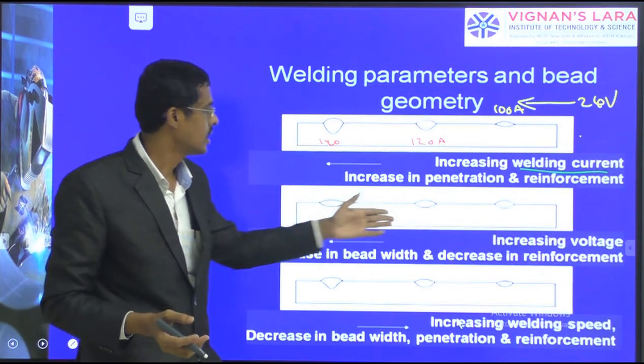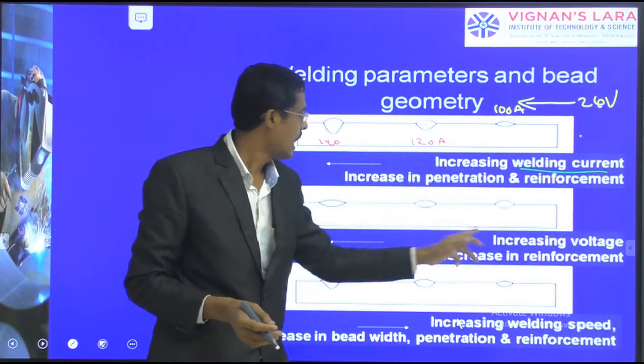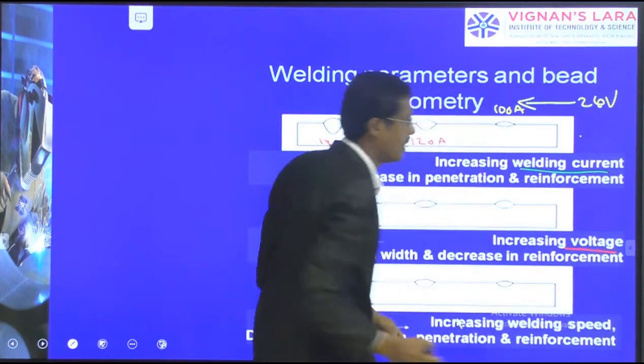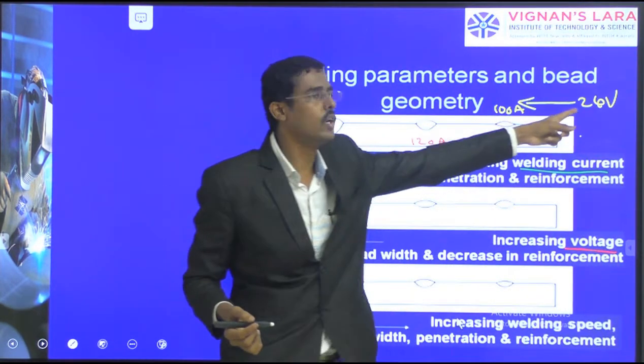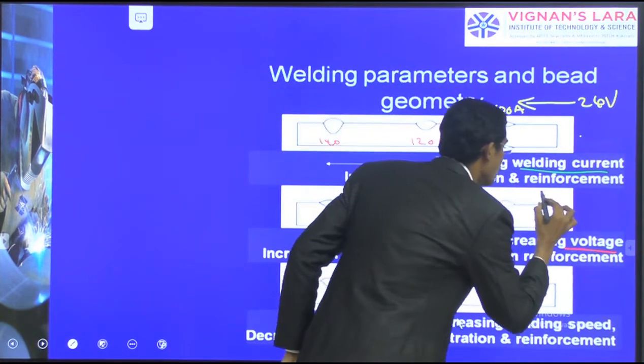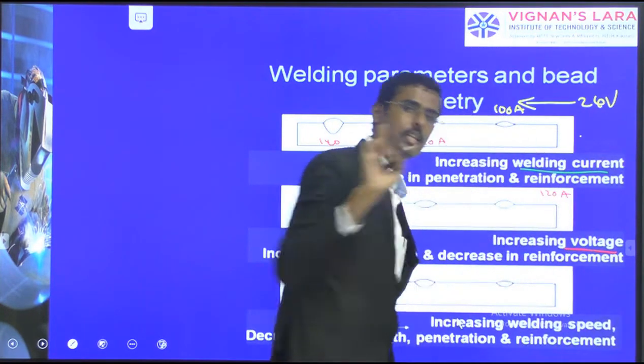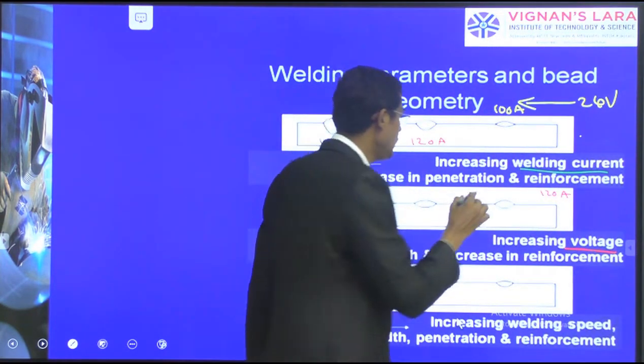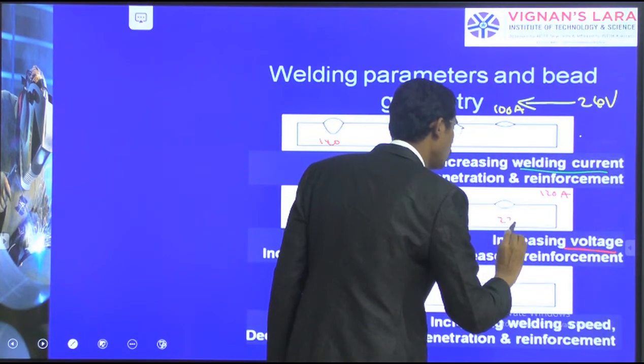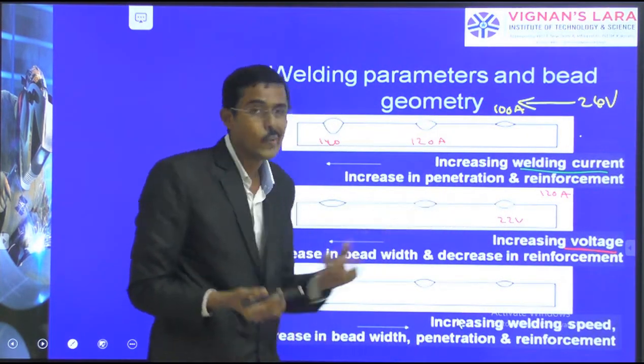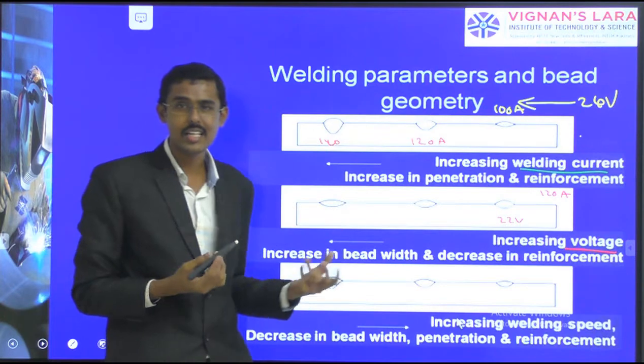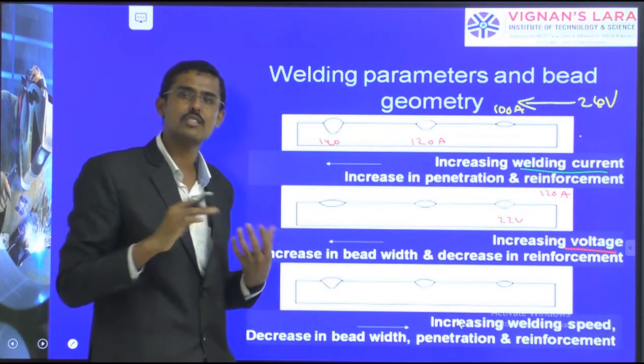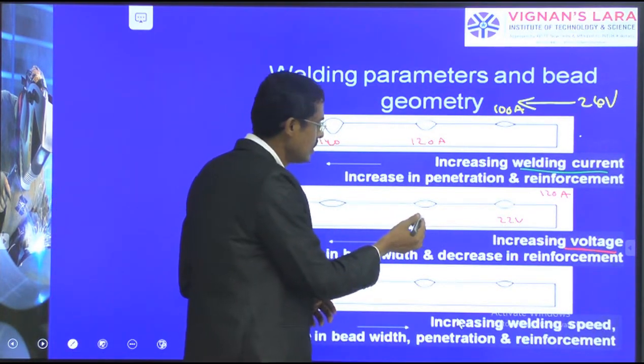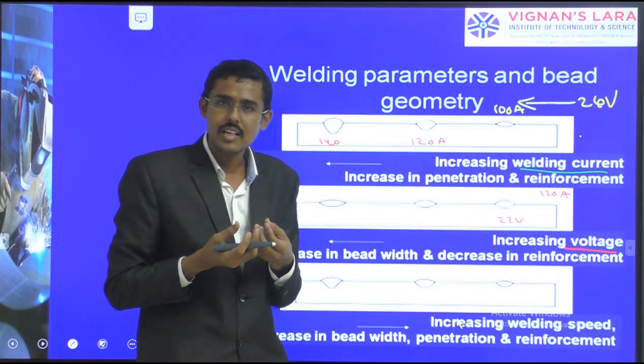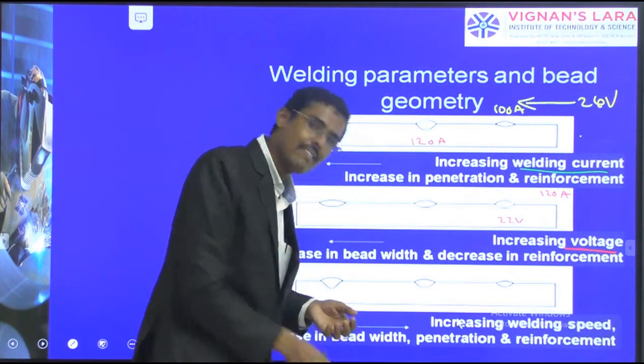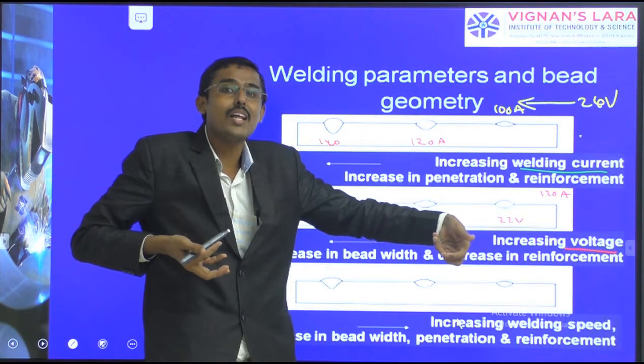That is a point: current increase, penetration increase. Now I am not increasing the current, I am increasing the voltage. I keep 120 amps constant and vary the voltage. Here I am giving 22 volt. What happens? It is minimum. The required is 24 volt. The pushing of electrons does not happen. It is not reaching the penetration level, but it is reaching somehow to a broader level.